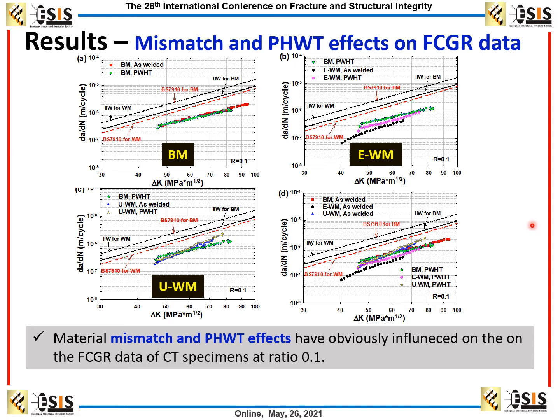The FCGR result is presented in this page. We compared the base metal, even matched weldment and undermatched weldment, and the stress ratio, R = 0.1. From the result, we can see the FCGR comparison between the as-welded and the PWHT states conducted for these materials. The FCGR of base metal isn't influenced by the PWHT processing in the first figure, which means that there is no residual stress effect on the FCGR in the base metal.